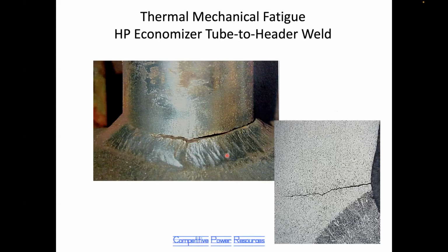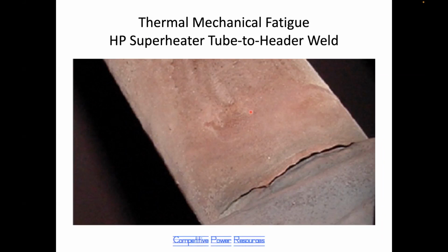This is a photograph of a typical thermal fatigue crack in a weld. It occurs at the toe of the weld in the tube material. This is very characteristic. Here's another photo of another one.